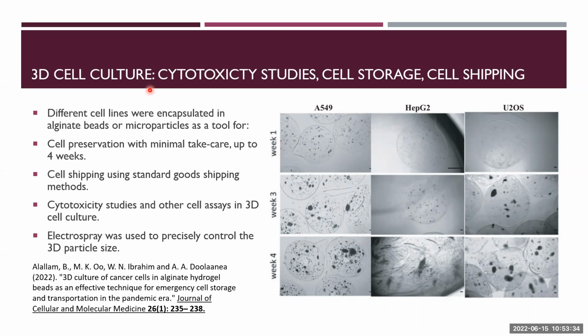Using high voltage, you can encapsulate the cell in the particles at controlled size, which can give you a reproducible size. The size is important for encapsulating the cell here, as this is used as a 3D cell culture model. In a 3D cell culture model, the bigger the size, the deeper the cells are inside. So the nutrients have to travel longer, and the cells are far from the nutrients in the solution. So it may get hypoxia inside.